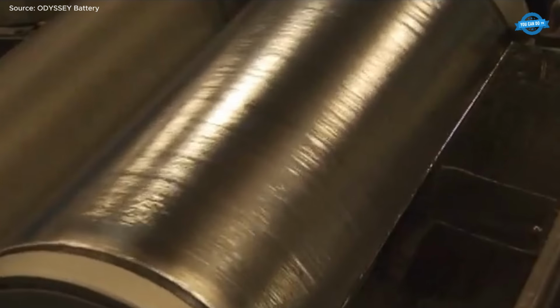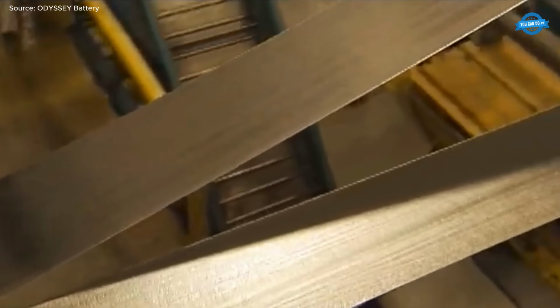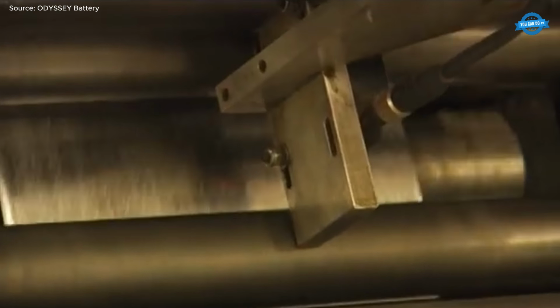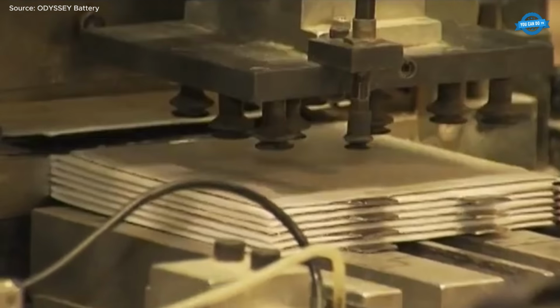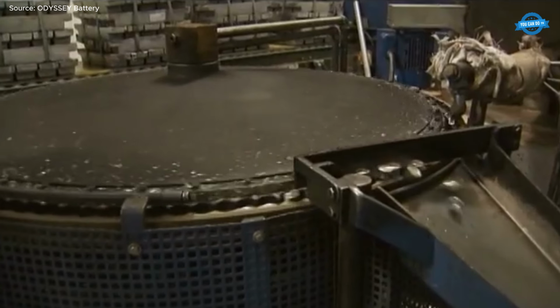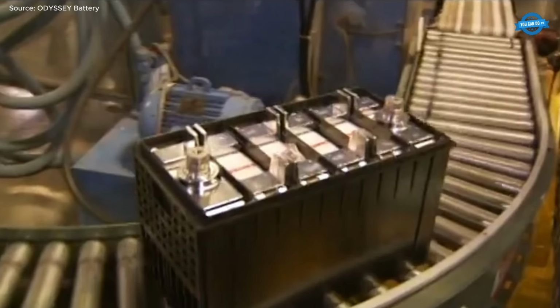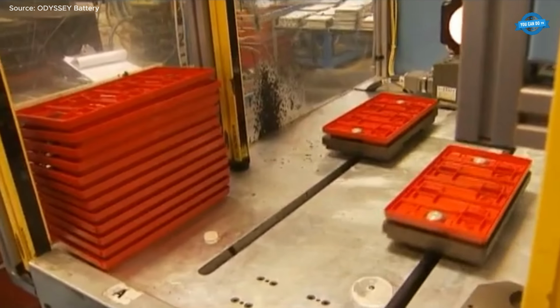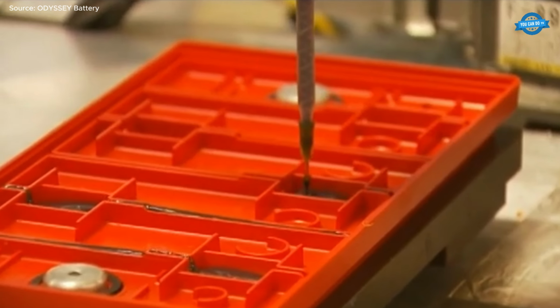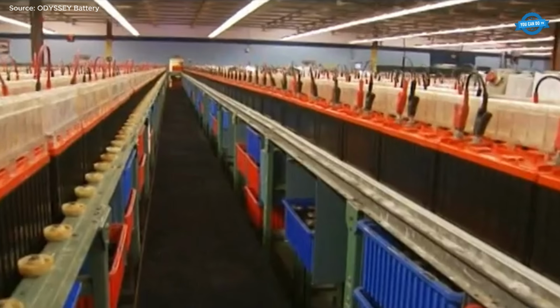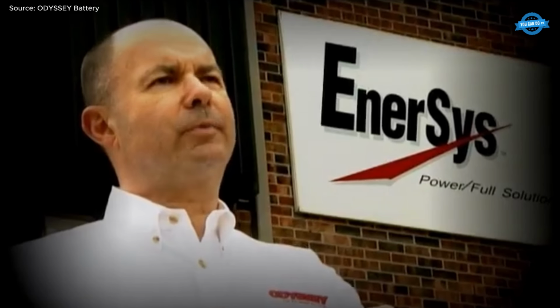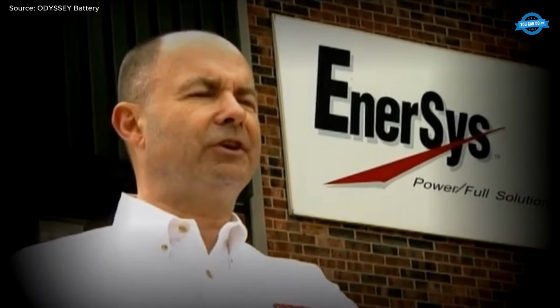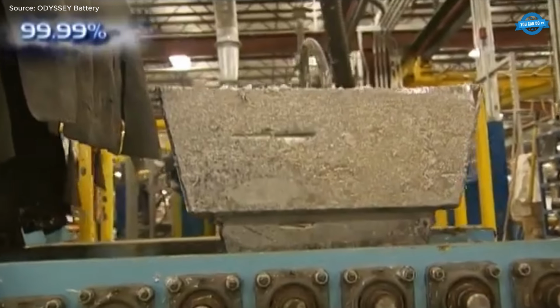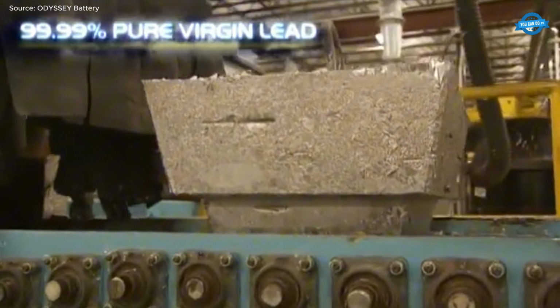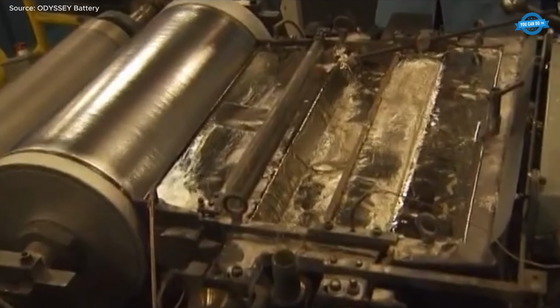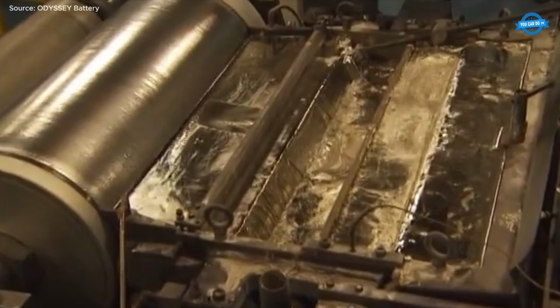Inside the Warrenburg facility, the Odyssey dual-purpose battery is built with one mission in mind: deliver uncompromising power. At the heart of that performance is TPPL, thin plate pure lead technology, made possible by using 99.99% pure virgin lead sourced from North America. This ultra-clean chemistry allows engineers to form exceptionally thin plates, dramatically increasing surface area and unlocking both massive cold cranking output and true deep cycle durability, with up to 400 cycles at 80% depth of discharge.